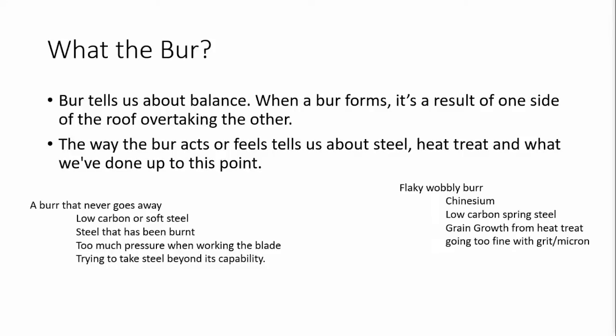Nine times out of 10, cheap Chinesium with less than 0.4% carbon in the steel. Low carbon spring steel, 1045 and 1065, are notorious, if you don't heat treat it properly, for having a very flaky and very feathery burr. It can also be caused by grain growth from heat treatment. Basically what that means is that the grains of the physical steel have gotten too large. And so what you're seeing is very large bits of carbide and other alloying components that have kind of clumped together and are still holding on. And when they flake off, you're left with sort of a micro serrated, warpy edge.